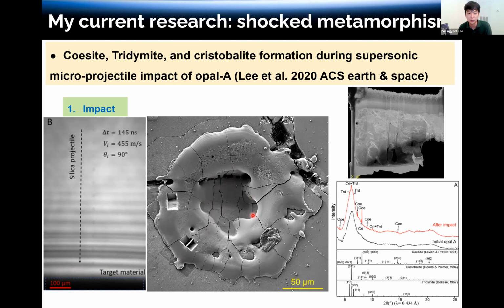And then this is an SEM image of the impact area. And then I can take out a focused ion beam sample from the interesting area, and then I can observe the TEM. Also, I can measure the X-ray diffraction pattern, initial and after impact. Actually, I did the opal-A mineral impact experiment. So after impact, this opal shows tridymite and cristobalite, high temperature, high pressure minerals after impact. So combining TEM and synchrotron X-ray diffraction is a very powerful tool to study the shock metamorphic process. So I plan to apply this method to more materials.